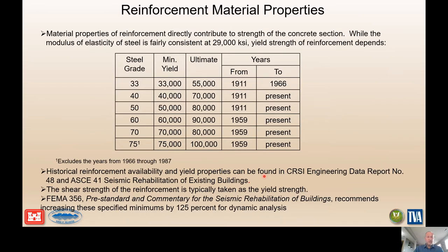Reinforcement material properties are obviously very important. For older hydraulic structures built 80 to 100 years ago, in many cases you won't know exactly what the material properties are — specifications may even indicate that reinforcement was furnished by the government. Just because you don't have that data doesn't mean you can't make an assessment. There are references that, based on the vintage and age of the structure, allow you to estimate yield and ultimate strength. The risk analysis conclusion may point toward actually going into the field to obtain these material properties.